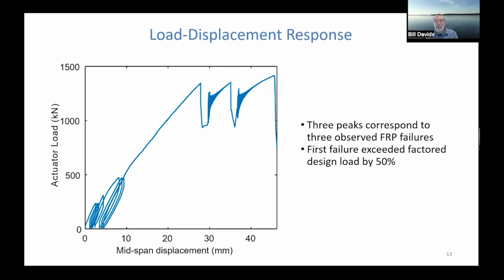And you can see that there are 3 peaks on this curve. We get a first failure at 27, 28 millimeters of displacement, a little over an inch, go another 7 or 8 millimeters, you get another failure. And then you can see out there at 47 millimeters, or close to 2 inches, the true peak load was reached. And that was the final failure. At that point, the specimen was done.